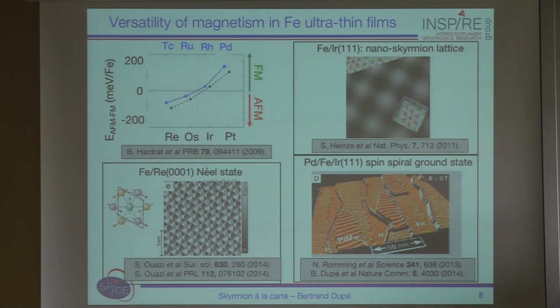It's a hallmark paper of 2009, where they look at the difference of energy between the ferromagnetic state and the antiferromagnetic state of an iron monolayer, a single monolayer on top of different 4d and 5d substrates. And you see that as you move from, let's say, the palladium substrate or the platinum substrate, which is very ferromagnetic, to the rhenium and the tungsten, you switch from a ferromagnetic ground state to an antiferromagnetic ground state.